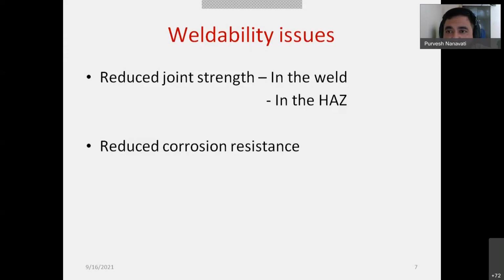This is a consequence of weldability problems, because most of the time, if you have heard of weld decay, you know that if there is more carbon, if it is not a low carbon grade stainless steel, then the carbon can combine with the chromium from the vicinity of the grain boundary and forms an intergranular cracking. So it's reduced corrosion resistance. It's a phenomenon known as sensitization of the weld metal.